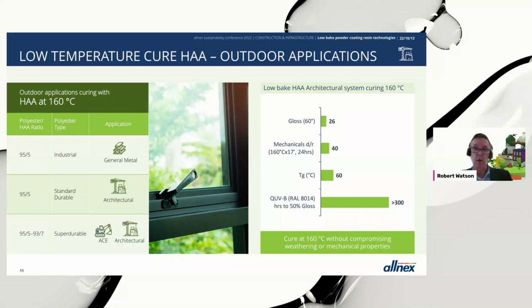And if we look on the right to see how some of these characteristics look, so this is a low gloss example with a gloss level of 26. The mechanical performance, direct, reverse, 40 inch-pounds, very acceptable for these types of polymers and coatings. The glass transition temperature, TG, is a good indicator of how storage stable a powder coating will be. And when we have a TG of 60, this is perfectly acceptable. And that last bar, the QUV, this is an example of accelerated weathering, and a typical pass is 300 hours to 50% gloss reduction. And we can see with this particular system that all those parameters are being met. So we can cure at lower temperature with HAA without any compromise in the performance of the coating. So this is a big step in the right direction.